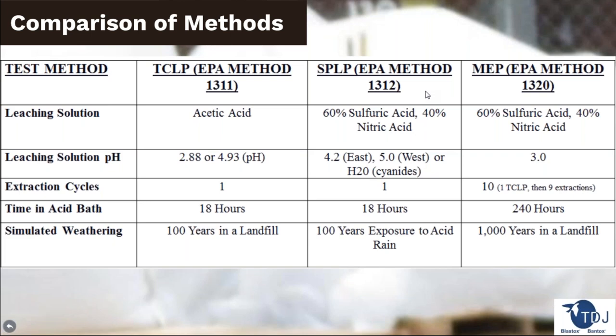In the last column, we have the MEP test. It has the same acid as SPLP — sulfuric and nitric — but at a pH of 3, so it's an even more aggressive solution. There are nine total additional extractions after an initial TCLP test. They run a TCLP with acetic acid replicating disposal in a sanitary landfill, then take that same sample and put it back into sulfuric-nitric acid simulating acid rain exposure nine more times. With a low pH acid and ten total extractions, you eliminate any potential buffering capacity, and it's estimated to replicate about 1,000 years of exposure.